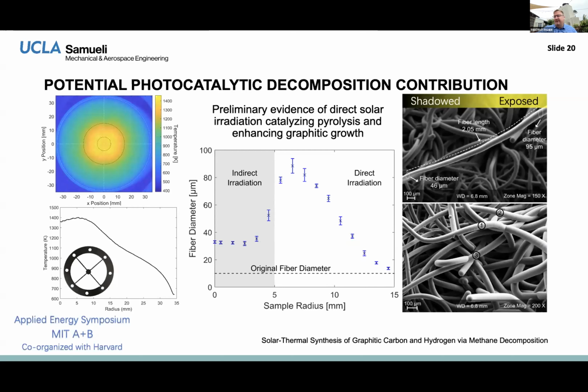So here's my speculation. I'm too old, like I told you, I've got grandkids, I'm told to be persnickety about the things that I'm thinking about. So here's what we think is happening. We think that as the methane approaches the porous absorber deposition substrate, it's heating up. There's translational energy exchange, molecules colliding, and so forth. So it heats up and starts to react a little bit upstream, but the actual residence time of methane in the reaction zone is only about 50 milliseconds. So everything needs to be really, really fast, especially to get these kinds of growth rates. We think what's happening is that there's a partial decomposition.